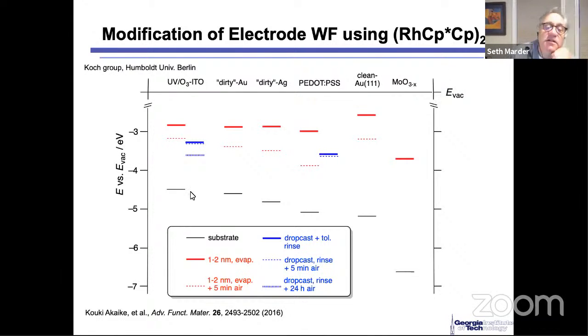So the point is that if you look at every one of these materials, there's a substantial drop, like a 1.5 volt drop in the work function. And in fact, for just about all of these, with the exception of doping the moly oxide, the work function goes below 3 electron volts, which is pretty low. And I'll show you on a couple of slides, it's really quite low.